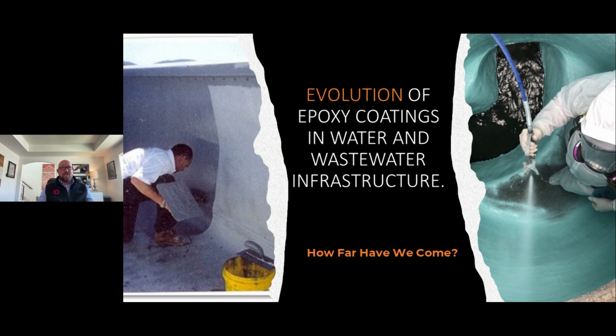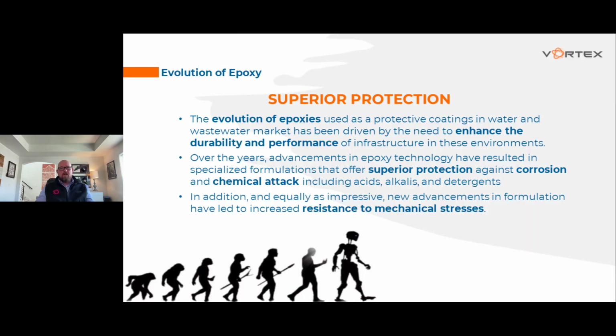This slide, for instance, shows the evolution in itself. On the left there, you see a person that's actually installing coal tar onto a tank. And then on the right, you see the installation of the structure guard material into a manhole environment. So through the evolution of epoxy, what we've been able to do is make these protective coatings. Like I already told you, they're very durable and they've got great performance, but we are also able to offer superior protection against that chemical attack in these environments. And then, like I mentioned a little bit earlier, we have a resistance to those mechanical stresses. And so that evolution has allowed us to go from a very thin build coating that didn't last very long in these environments to a high build coating, up to 250 mils in a single pass, and give you about a 50-year design life.